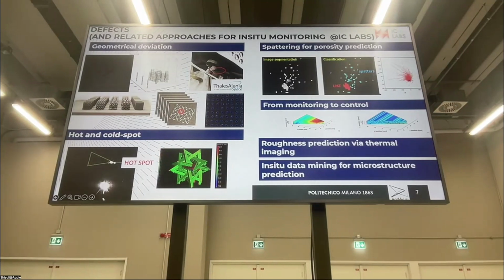The first, and we'll spend some time on this, is just taking a picture. Since the process is additive, it's happening layer-wise. So at each layer, you can take a picture and investigate the shape of the layer that has been melted, and see if this final shape coincides or has some discrepancy with respect to the nominal shape. So it's some sort of layer-wise quality inspection, just by comparing the melted zone with respect to the nominal zone, the nominal shape, and being able to detect as soon as possible some discrepancy that can result in a final defect of the part.